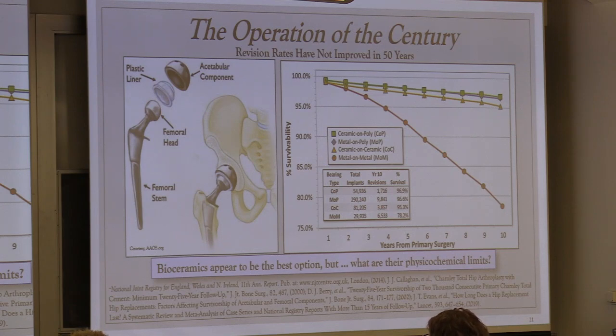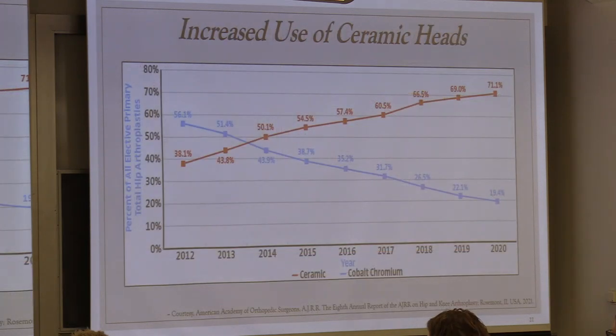And how could it be that they allowed this to happen? It's a sad case. The problem is that there has been a lot of experimentation on basically patients in hip arthroplasty, but fortunately, as these curves show, more and more physicians are focused on going to ceramic-based components as opposed to metal-based components. So the switchover has occurred, and most femoral heads now, except for the extreme elderly patients, tend to be ceramic heads. And the reason is, as the prior slide showed, they present better survivorship over the long run.